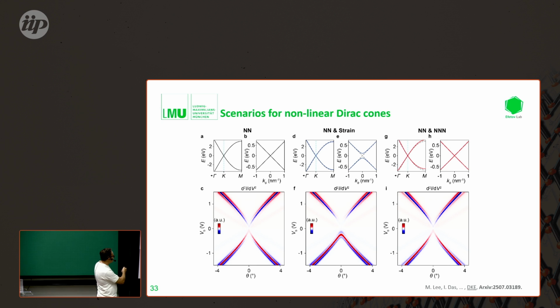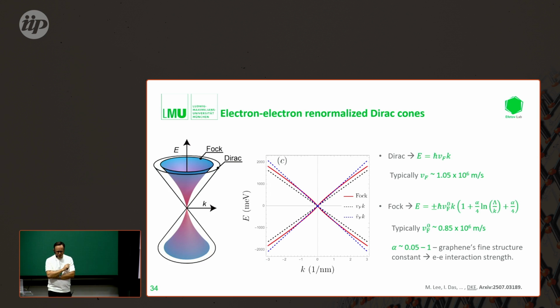Third, next nearest neighbor hopping was also famously reported to produce some nonlinearity, but these next nearest neighbor hopping terms actually give electron-hole asymmetric deviations, and also at much higher voltages than what we observe in our devices.